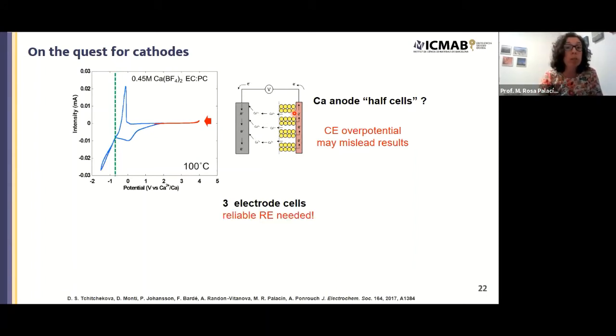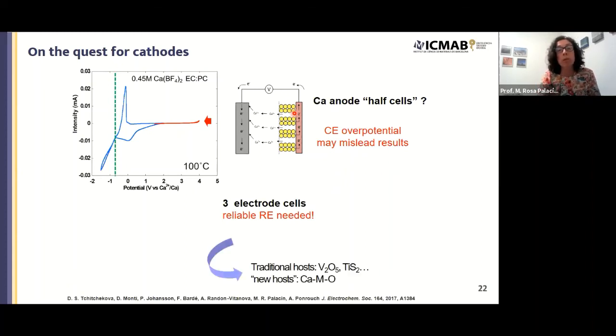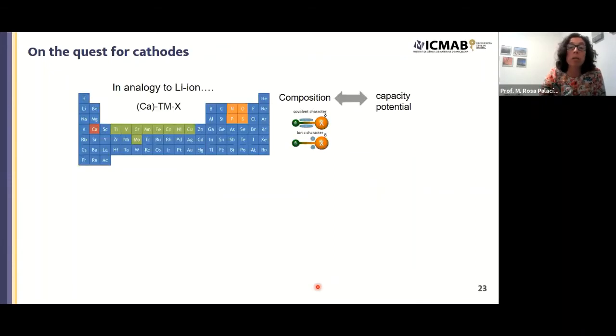And then the issue is which is the best reference electrode, and this is not trivial either. We started using calcium metal, but then we need to calibrate it because there are some relevant differences between what would be expected from the standard reduction potential and what we observe. But once we had developed all those protocols, we were ready to start testing materials. And we focused on two types of compounds. First, traditional intercalation hosts like V2O5 or TiS2, or other compounds which would also contain calcium in the crystal structure, and basically calcium transition metal oxides.